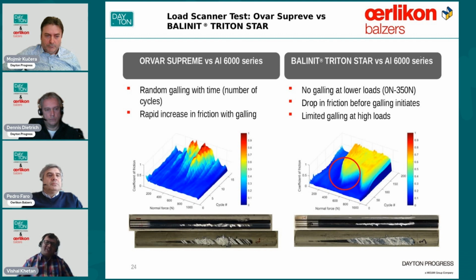And further, at higher loads also, the galling is not significant enough as we see for bare steel, making Triton Star an ideal solution for aluminum punching and stamping applications. So these kinds of tests have helped us work with our clients to choose the right solution for them, Triton Star being one of the best, I would say, average solutions. And if there are special needs or we need to modify something, we can do it directly with our clients using these kinds of tools which we have available in-house.